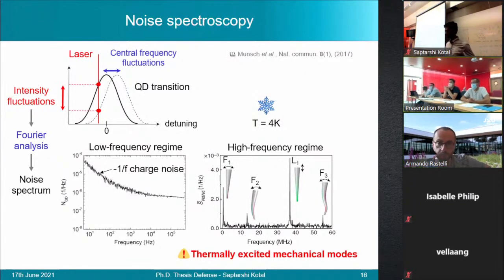So the frequency, you mean? The temporal resolution, yeah. So that would be limited by the broadening, a radiative lifetime, which is around 0.7 microelectron volts that they measured, and that's equivalent to around 160 megahertz in terms of frequency. So it would take as many modes, up to the 160 megahertz range of frequency modes, would be able to be detected, because they would fall into the radiative linewidth.